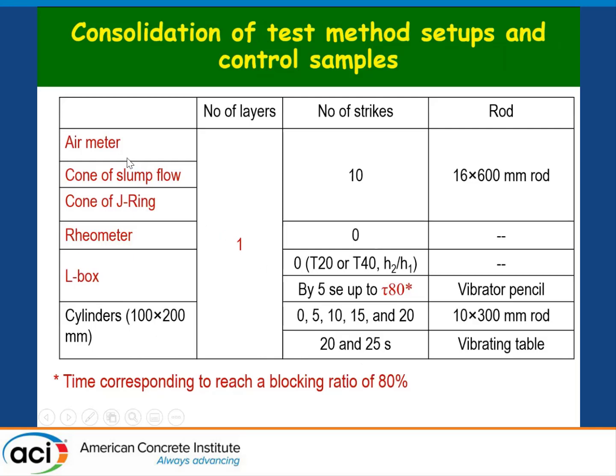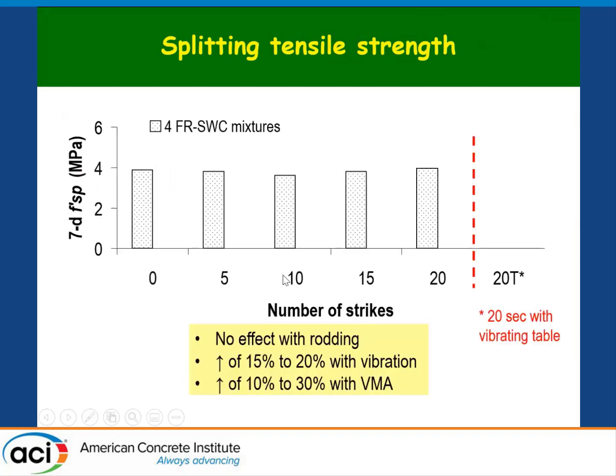Now, we also tested the unit weight and air volume, slump, J-ring, rheometer, L-box, all of these test methods. We filled the containers using 1 layer, and we subjected the containers to 10 strikes using the rod that typically is used for the slump test. So 10 internal vibration. And then when we came to the cylinders for compressive splitting tensile strengths, we used smaller rods, 10 millimeter rods that are used for 4x8. And again, different amount of strikes versus vibrating table.